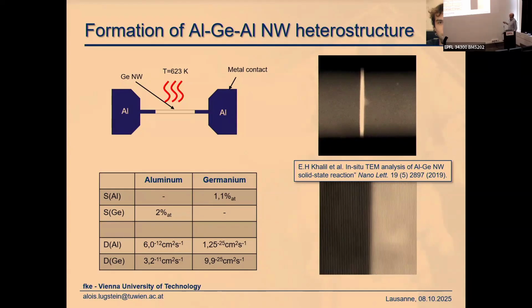This is the interface of the remaining germanium, which is single crystalline, and happily also the aluminum that replaces the germanium is single crystalline. So by this exchange mechanism, we can make very small dots, quantum dots, which are connected in a self-aligned process to real metal contacts.